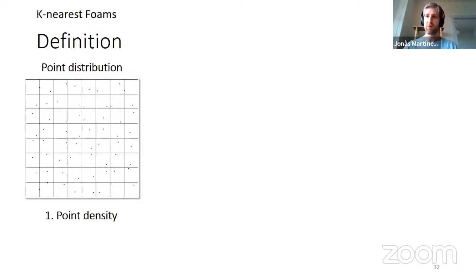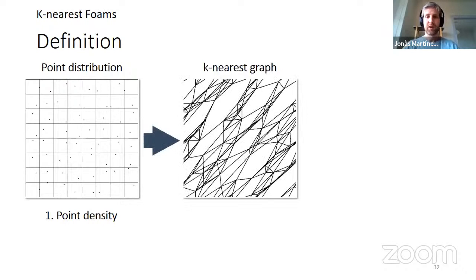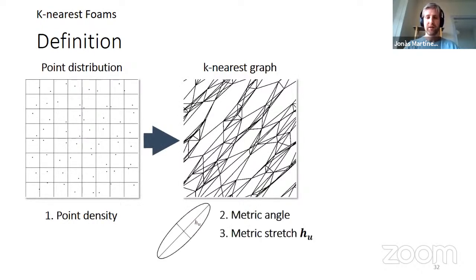And I'm going to show you truss materials that follow a laminate structure. So what we did is to consider basically a k-nearest graph of a set of points. Again, you have an input point distribution, and for each point, you link it to its k-nearest neighbors. For instance, with k equals 6, you link it to the 6 nearest points. And you can do that considering some metric. In our case, we consider a distorted metric, which is basically the Euclidean one with some affine deformation.